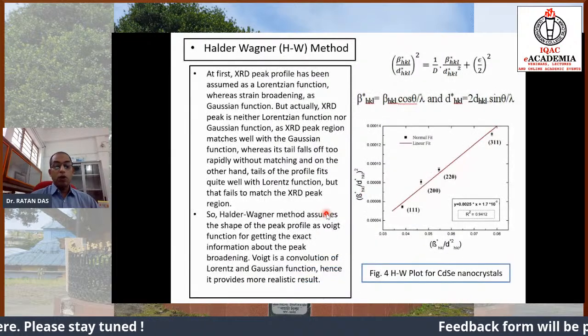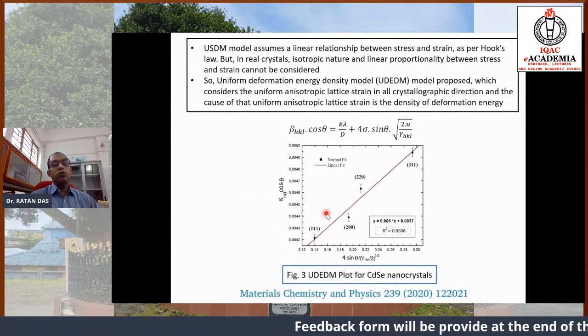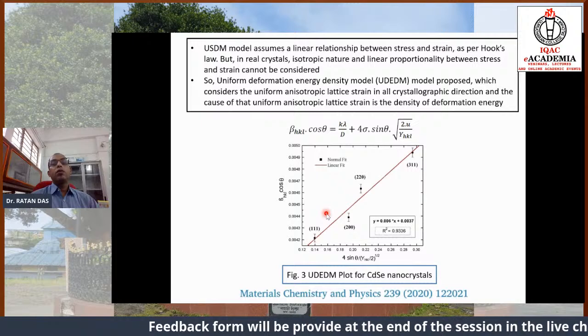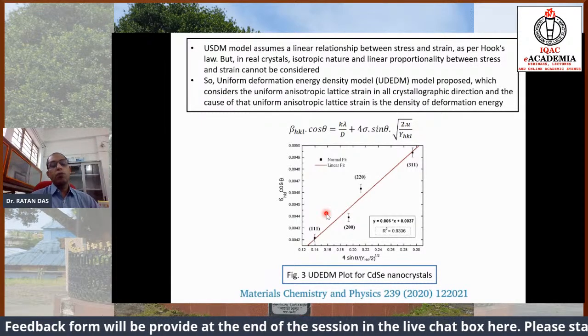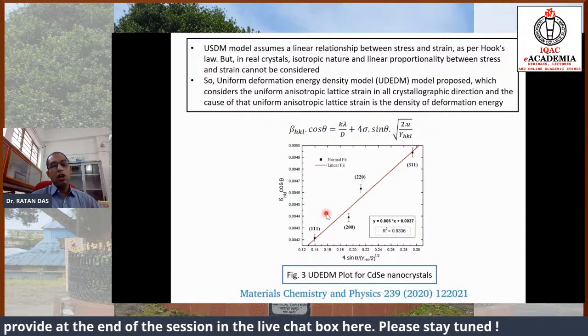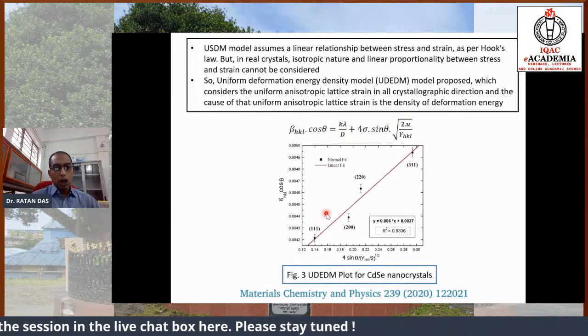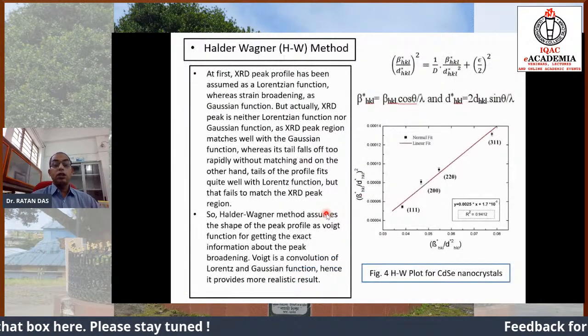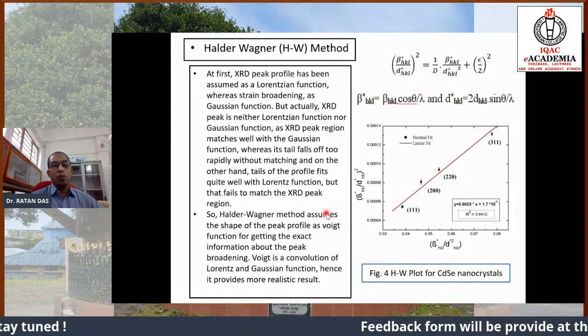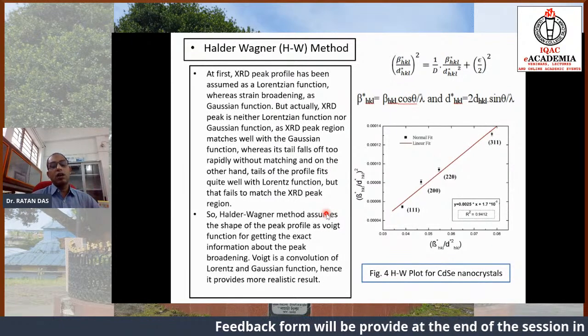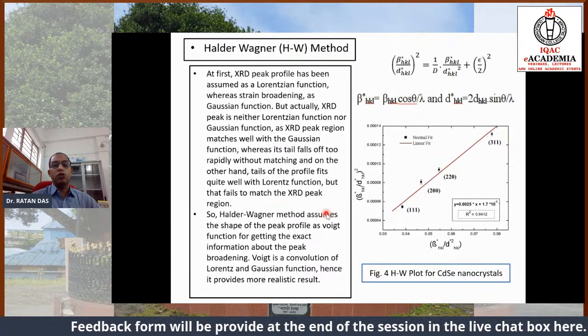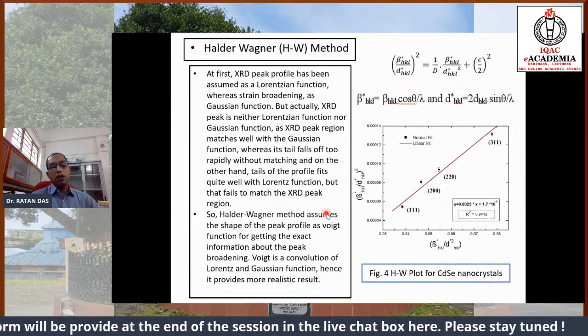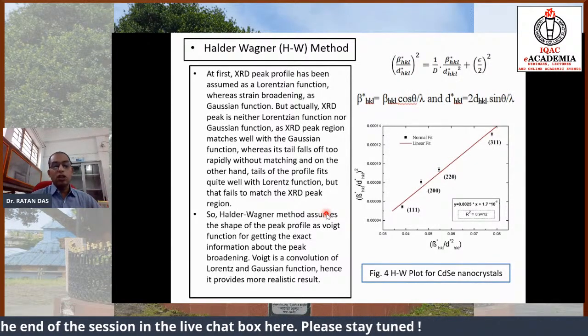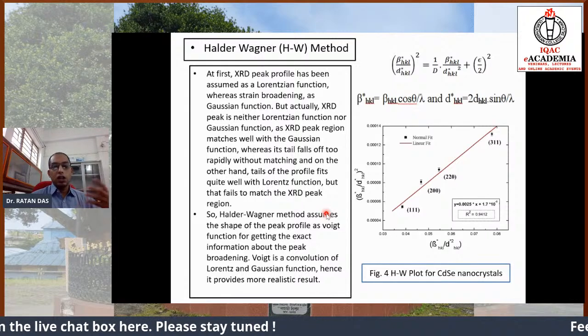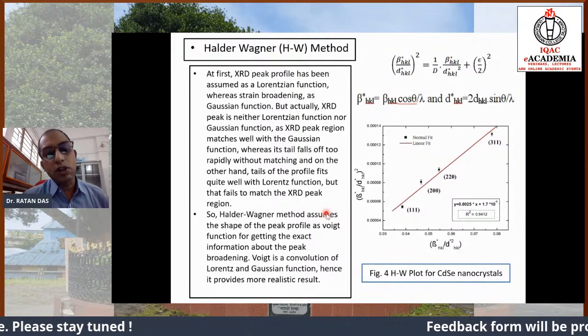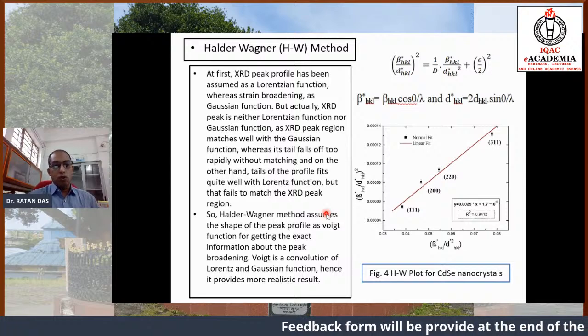So what I want to say is that by using different models of the Williamson-Hall method, we can obtain the stress, the strain, the Young's modulus, and the energy density present in a nanoparticle. Obviously, these are the average of all the nanoparticles, but we can say that the intrinsic strain, the internal stress, and the internal energy inside the nanoparticle can be obtained from the Williamson-Hall method.